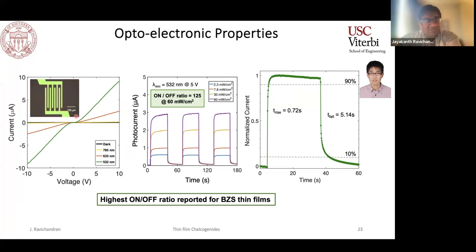We also had some work suggesting that polishing these materials would lead to a lot of deformation twinning and other extended defects. So once we were able to figure that out, we showed that we can get fairly good on-off ratios. There is still a sufficient amount of defects. That's why you do see photoconductive effects here. But nevertheless, this behavior is significantly better than what other people have managed to report and similar in other thin film materials of this BaZrS3